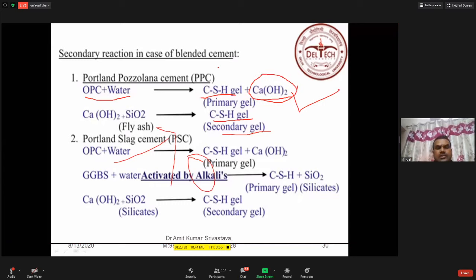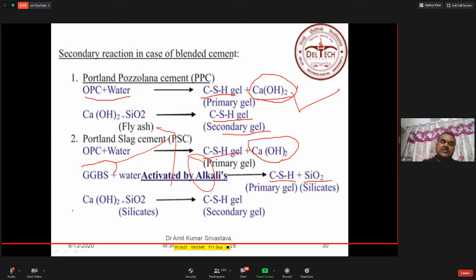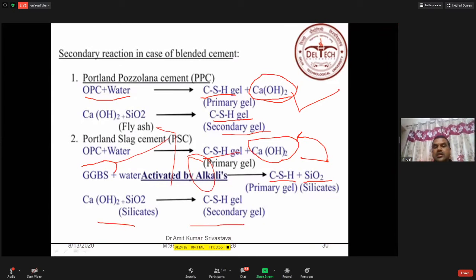Similarly, we have another variety of material called Portland slag cement. We are using GGBS here. So once I add OPC plus water, I am getting CSH gel, the primary gel. Then again, this calcium hydroxide is unused. Now GGBS reacts with the water and forms CSH and silicates. So I am getting another CSH as a primary gel, and this SiO2 reacts with the calcium hydroxide and forms another CSH gel. So the quantity of CSH gel formed is more and more, and we are getting better and better concretes. So if I use this type of supplementary cementitious materials, we not only get better strength, but also better durability, because it is going to protect your reinforcements.